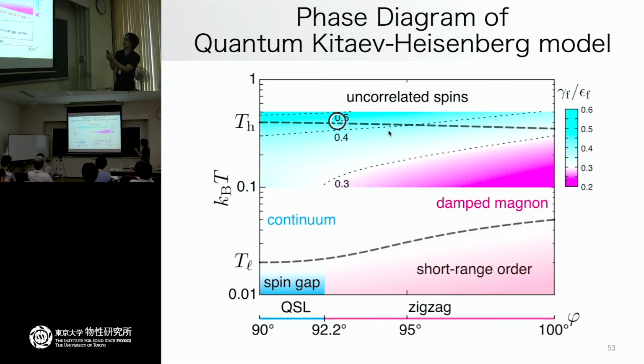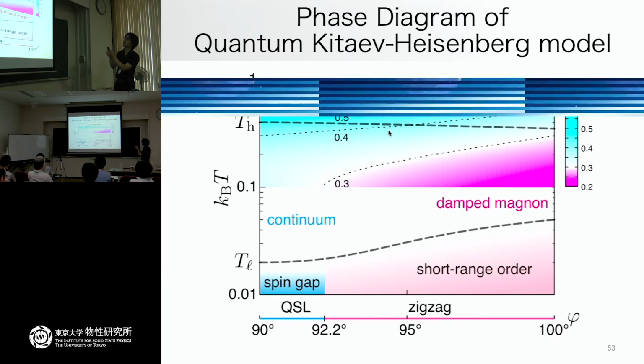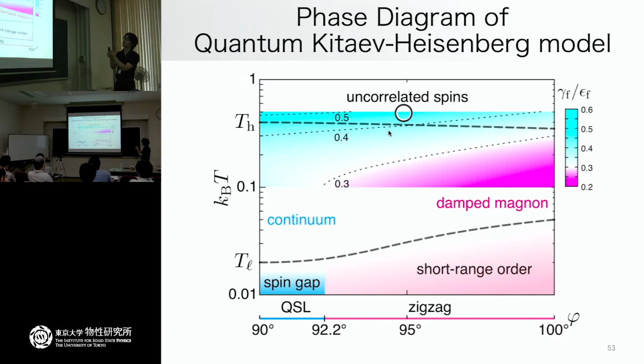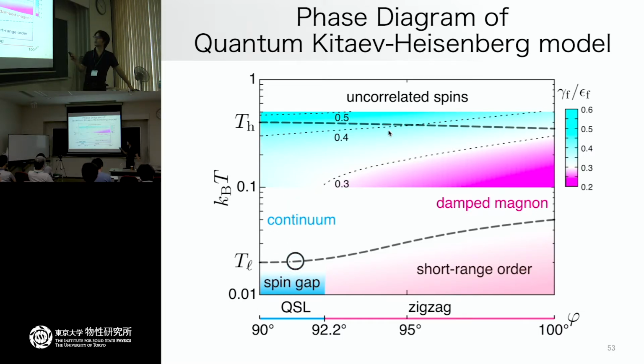Starting from high temperature, this ratio is more or less one half above this high temperature peak. This corresponds to uncorrelated spin behavior. But if you lower the temperature below this temperature scale, this ratio becomes smaller and smaller. And in the high temperature region above the quantum spin liquid phase, it just stops above 0.3. If you check the temperature dependence, this ratio cannot become smaller in the quantum spin liquid phase, because we have continuum spin excitations there. However, if you go into this zigzag ordered phase, then this ratio can be smaller than 0.3.